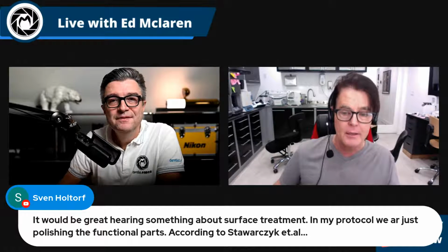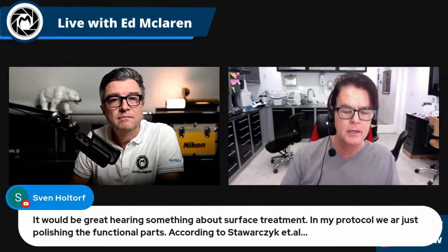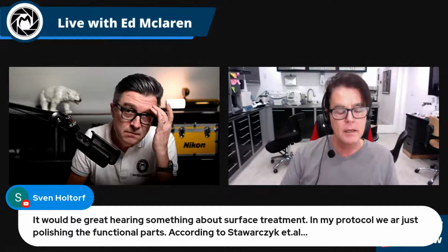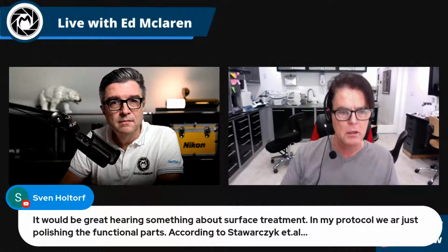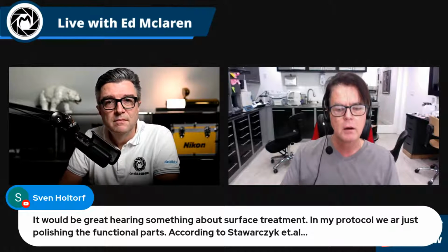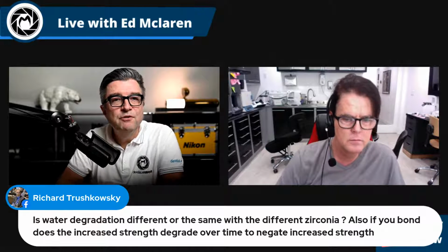So functionally, applied clinical aspects of what I've done, I glaze and paint the aesthetic surfaces. And I actually would glaze the functional surfaces, but then I polish off the glaze. I polish because some SEMs that we did, we showed sometimes there's some teeny tiny micropores, and basically I want any little microscopic pieces of glass to fill into those pores, okay? So moisture doesn't get in, and then I just polish back down to the zirconia. And actually John Burgess did a study where he looked at glazed, polish, and polished zirconia. And he found that the abrasiveness of the glazed polished was the same as the polished. But I think it's a better surface because I'm sealing any micropores. So yes, I agree with that paper, what they mentioned. So one question from Richie.